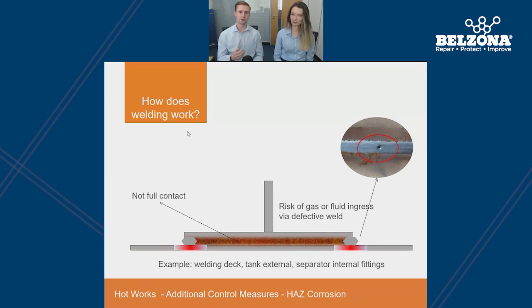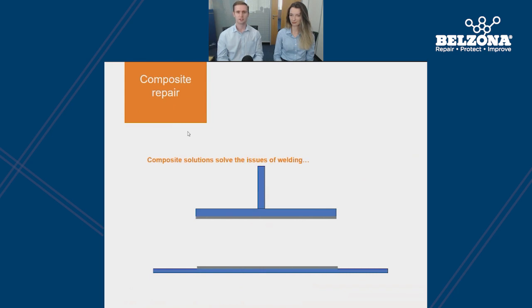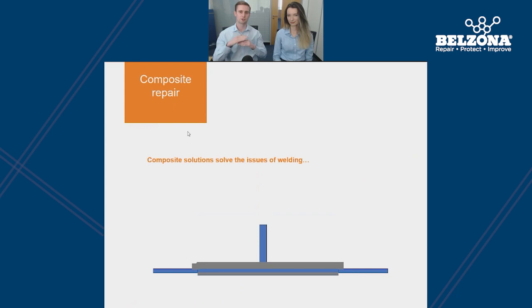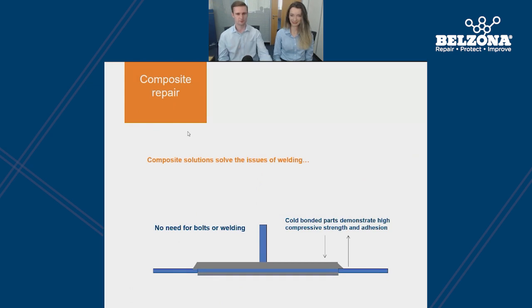And as mentioned previously, these welded areas have also created heat-affected zones. So this will change the microstructure of the substrate, which again could cause cracking later down the line. So we'll now look at the Belzona solution for bonding. So as demonstrated on the screen, the Belzona solution offers 100% contact on the substrate, which gives an excellent load distribution. The Belzona material, also being non-metallic, acts as an electrical insulator, eliminating any potential for galvanic corrosion and therefore offering a long-term corrosion protection.